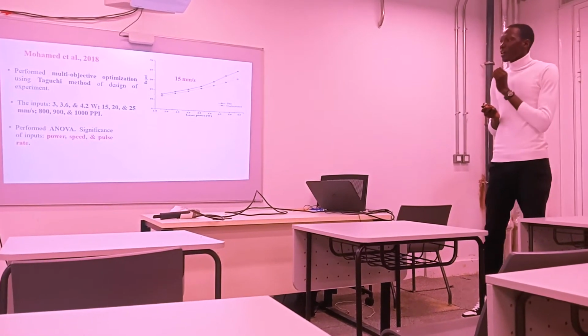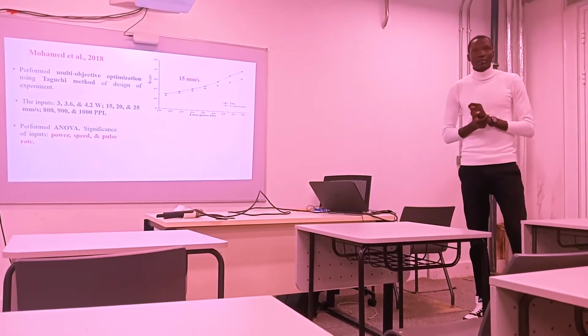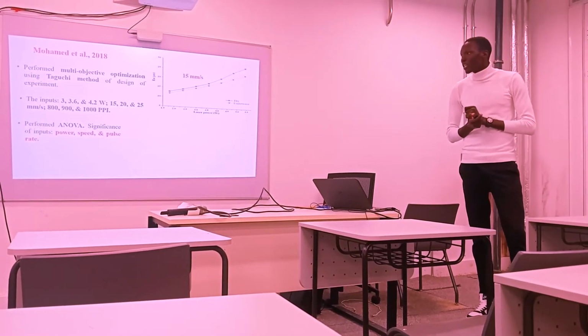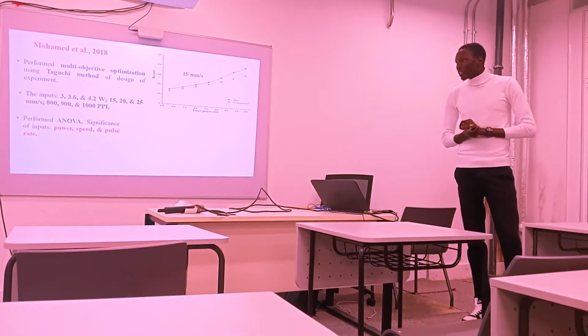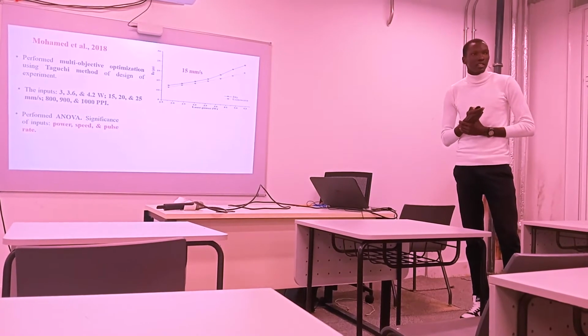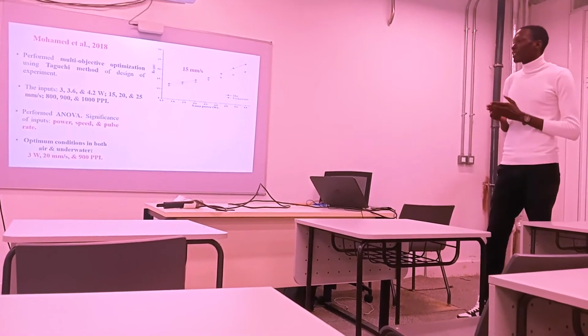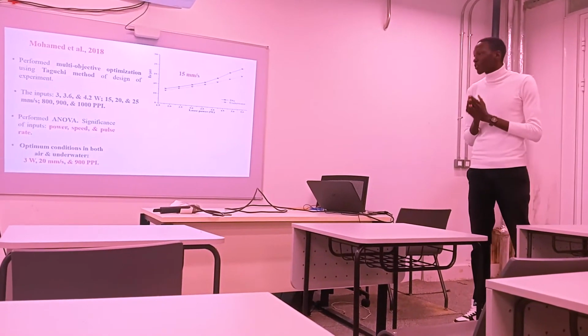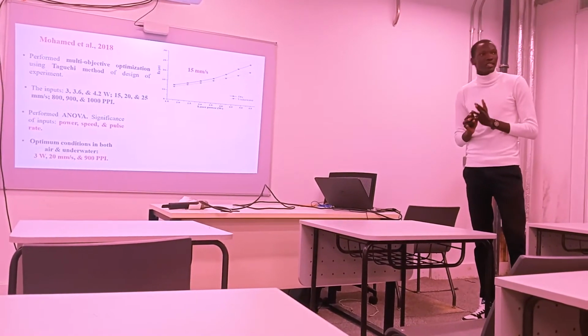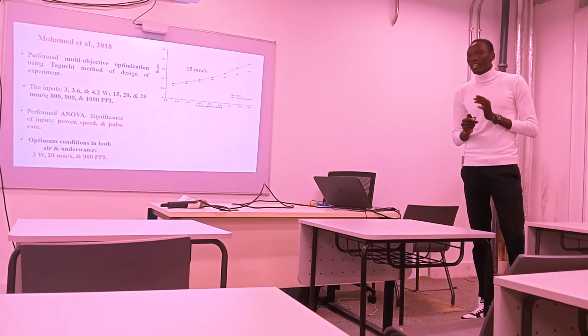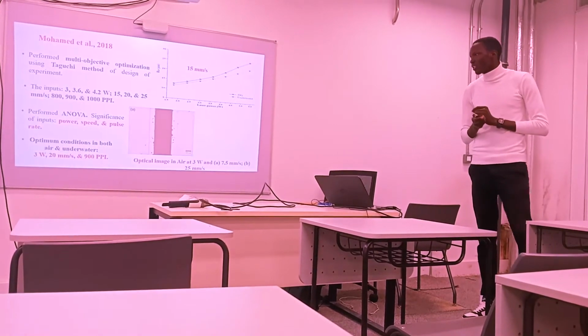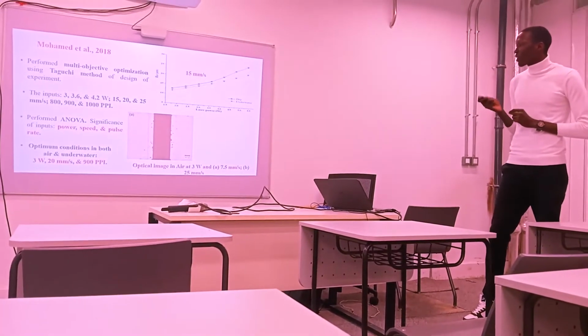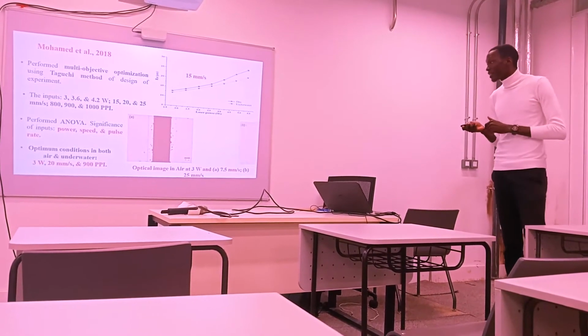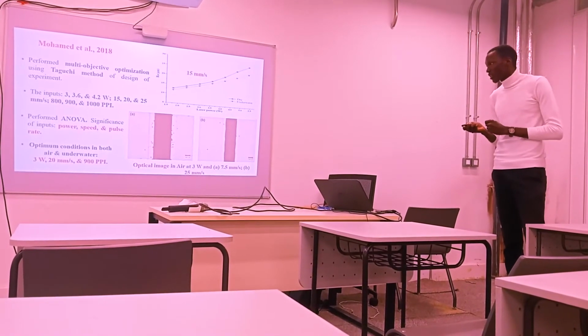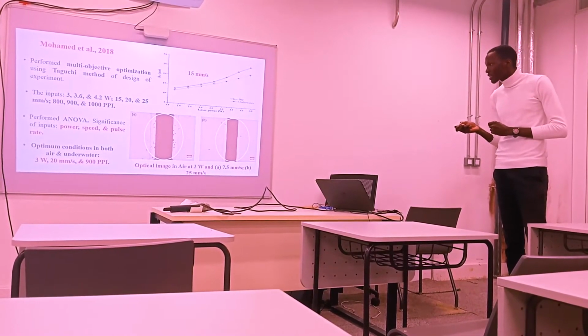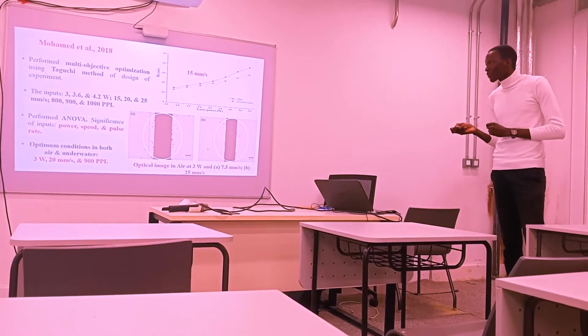Then they performed analysis of variance to find out the significance of the inputs, and they found that power is the most significant, followed by speed, and then pulse rate. They found the optimum conditions for fabrication in both air and underwater to be 3 watts, 20 millimeters per second, and 900 pulses per inch. Now, this is the optical image they found in air, and this is what they found underwater. This is really better than this. Underwater is better than in air.